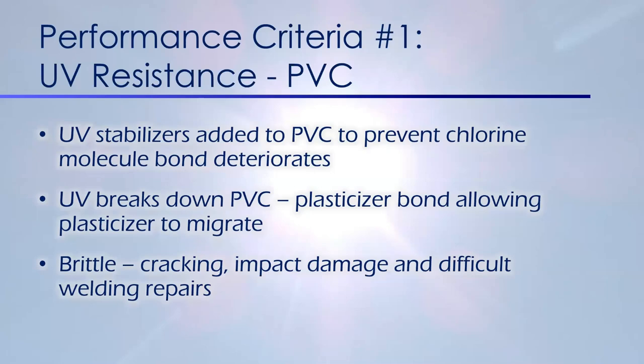When we look at PVC, PVC is a very tough and dynamic high molecular content product. It's very strong. It's very rigid, right? So what they've done in the manufacturing process for roofing is added a plasticizer that I mentioned earlier to PVC that kind of hinges the molecules there, making it flexible. Well, what happens over time to UV exposure? Plasticizers will migrate out of the sheet and they'll leave you with the exposure there, which then leads to a brittle product that is prone to cracking or impact damage and making it difficult sometimes to repair failures on the roof or patch and repair on a PVC.